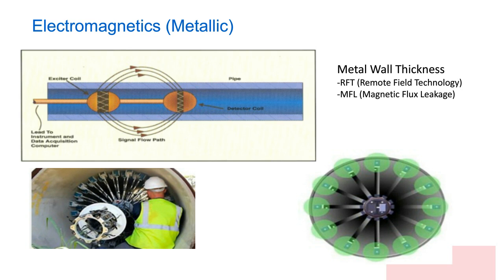It's incredible technology. It really gives you a very, very fine resolution and allows you to really assess the condition of the pipe, and from that assume whether it's in critical repair or whether you can do long-term repair, or maybe the pipe's even in very good shape. But that is the type of technology we use for metal wall thickness, and it's the same technology used for measuring whether there's any breakage in the pre-stressed concrete cylinder pipe, the metal wires. If there's breaks in the metal wires, then what happens? We have changes in the magnetic field flux. So that's just a quick overview and a very minor dissertation on how magnetic flux leakage works.